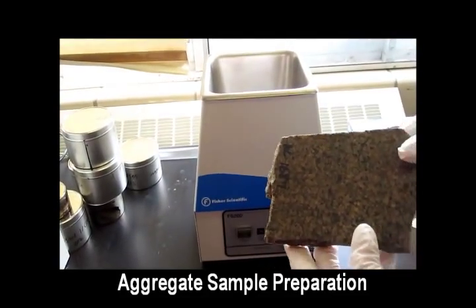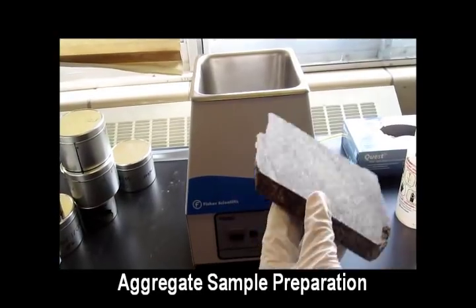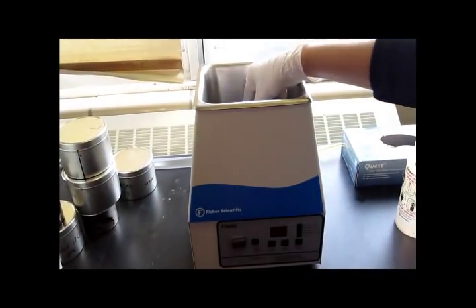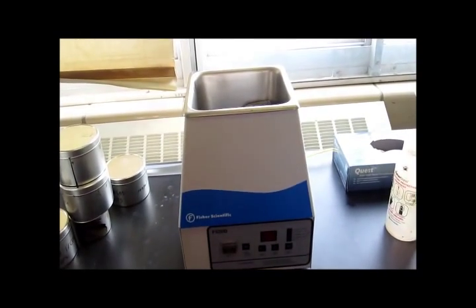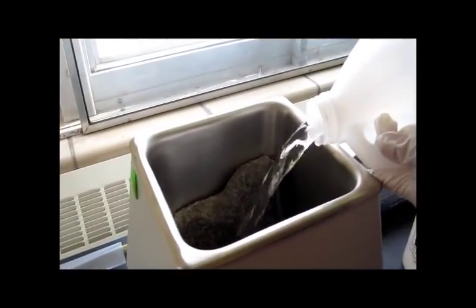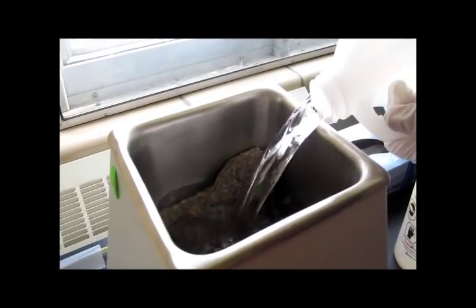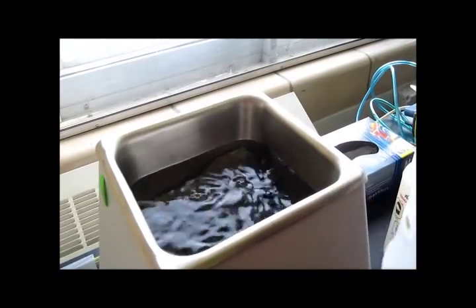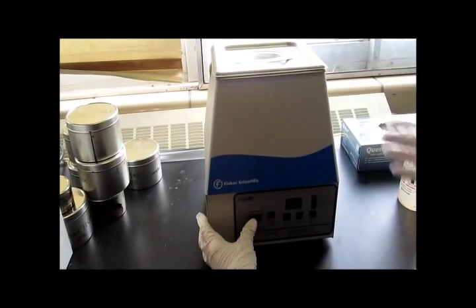Aggregate plates are cut with similar thickness and parallel top and bottom surfaces. After cutting and lapping, aggregate plates are immersed in deionized water in an ultrasonic cleaner with a sufficiently large tank to allow for complete submersion of substrates. It should be mentioned that the lapping is done to provide a control on the roughness of the surface.